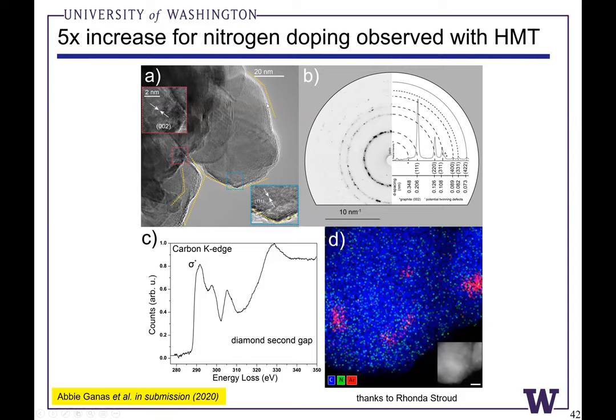This is a TEM image that Abby also got with Rhonda Stroud at the Naval Research Lab in Washington, D.C. Abby won a prestigious Goldstein Travel Fellowship to work with Rhonda and collect these very nice TEM images. You can see faceting, one-one-one facets of the diamonds. You can see sort of a quasi-amorphous or graphitic type surface reconstruction. We're currently analyzing these high-res TEM images using Fourier transforms to map out the phase distribution potential.